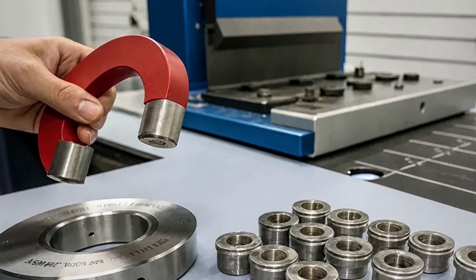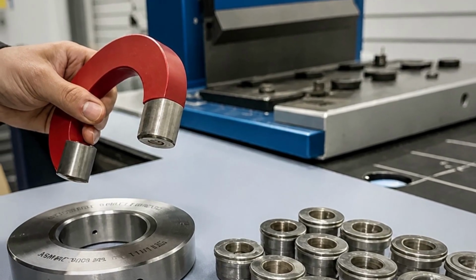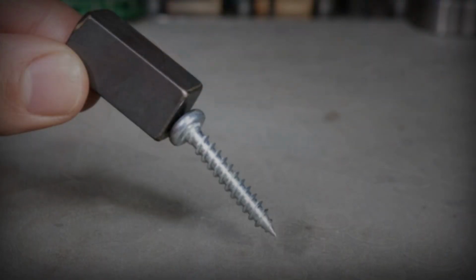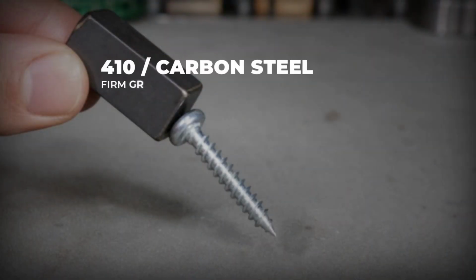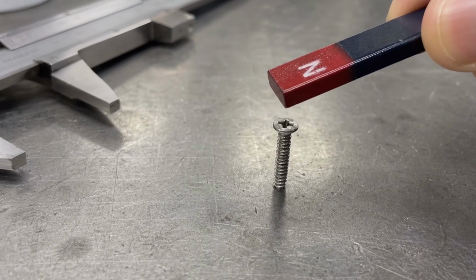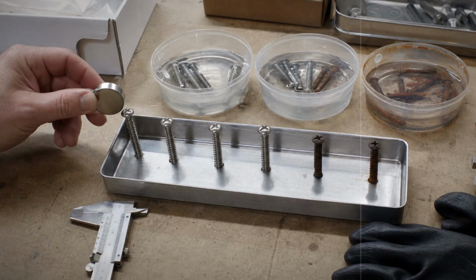The magnet gives you the 30-second version, and you can now read it properly. A firm grip suggests 410 or coated carbon steel underneath a finish. A faint pull is entirely consistent with real 304 that has been through a forming press, and it counts as no evidence of anything wrong.